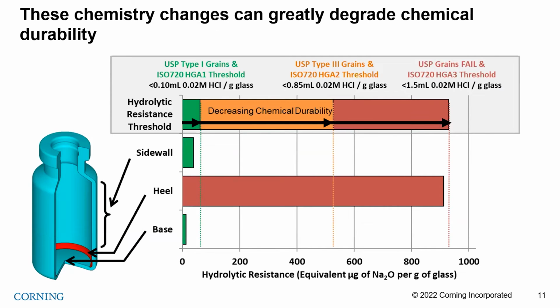But in those regions where the boron is greatly enriched, this is where we see really degraded durability. That heel region, you can see here, gives off a lot of extra sodium and boron in standard corrosion tests.